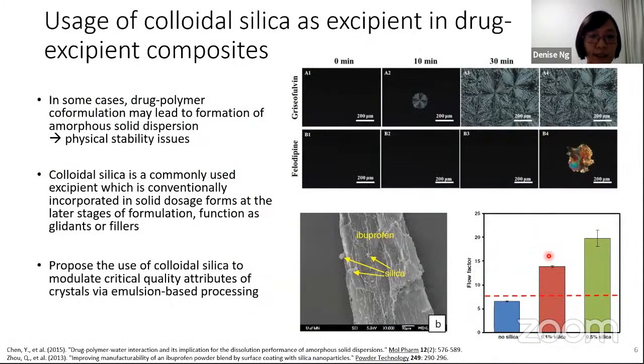However, in some cases, dissolving the drug and the polymer in the same entity may lead to the formation of amorphous solid dispersion. This may pose physical stability issues such as polymorphic transformation over time. In the case of griseofulvin and felodipine, it crystallizes over time, and this may lead to changes in the dissolution and therefore the therapeutic efficacy. Besides the usage of polymers, there are many other types of excipients available, one of which is colloidal silica. Colloidal silica is a commonly used excipient, which is conventionally incorporated into solid dosage forms at the later stages to function as glidants or fillers.